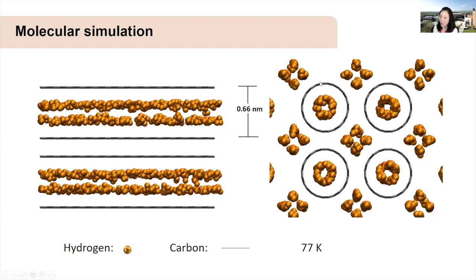On the other hand, if we look at the cylindrical pores, hydrogen forms a one-layer, spherical structure, with a certain amount of mobility. I think from this neutron scattering study, there are two conclusions or highlights. First, neutron scattering provides the evidence that immobile or solid-like hydrogen can be formed at a much milder condition. And secondly, the pore size is the key in hydrogen storage. Although pore shape influences the packing of hydrogen, especially at the engineering level, controlling pore size is more critical.